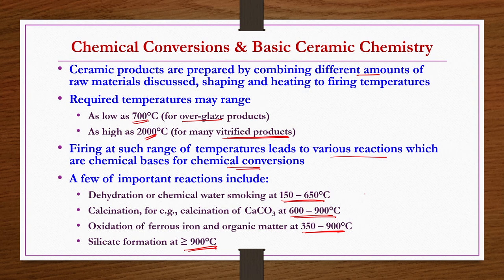Now, they do not take place individually, step by step. So you can see here, let us say at 600 degrees centigrade, dehydration may take place, calcination may also take place, and even oxidation of ferrous iron materials may also take place, right. So, at a given temperature, more than one of these steps may be possible, but at temperatures more than 900 degrees centigrade, only silicate formation takes place. Silicate formation taking place means product formation is taking place, right.